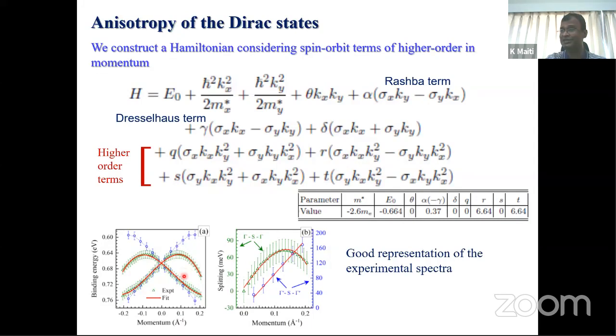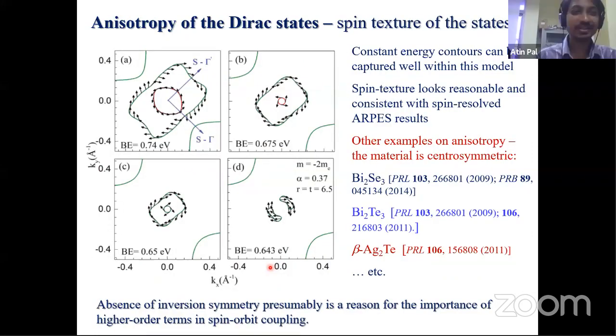And the spin splitting, that means this is up and this is down, or this is up spin, this is down spin, whichever way you define. So this splitting, you can see along this vector is different from this along other vector, and we could actually capture all the scenario. Okay. So maybe you can finish. Yes, this is the last slide.